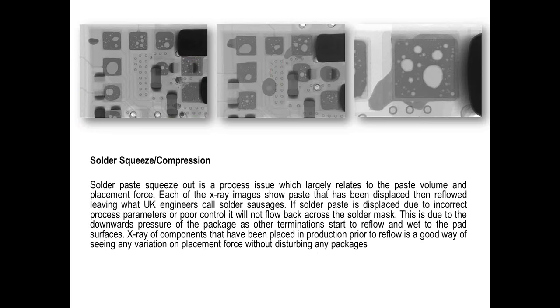Now, solder squeeze out and compression, in my opinion, tends to be more related to the assembly process prior to reflow. What I've got here are some examples of what some people call solder sausages, where you've literally got lumps of solder not necessarily where you want them to be between terminations. A key thing when you're looking at any bottom-mounted termination component, a QFN or LGA, is not to compress the solder paste during placement. Control the placement pressure. Make sure you're making contact, but you do not want to have displacement of the paste away from the pad area.